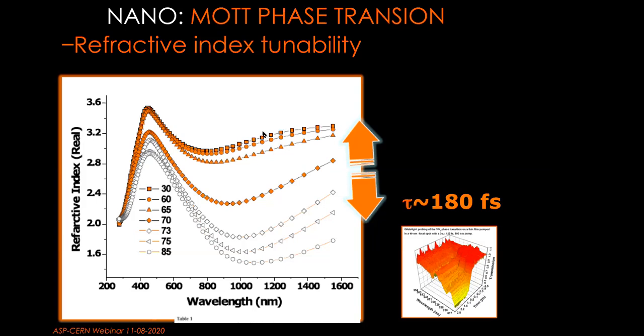It shows you, simply said, the refractive index variation with the temperature versus the wavelength. If you go to the Bible of optical materials that we call Palik, you will never find a material whose refractive index changes so much. And see here, for example, at 1000 nanometers, that means near infrared radiation, the refractive index moves from 3.2 to nearly 1.6, which is twice.